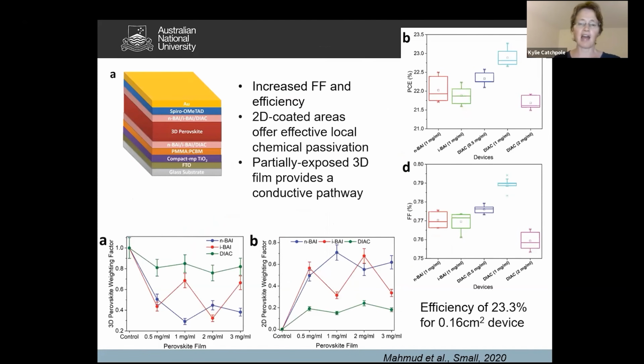Now, interestingly, there are other ways to achieve that. So what we're doing here is a quite different approach, but the net effect is actually very similar. So here we've got a perovskite layer that's passivated with a mixture of N-butyl ammonium iodide and isobutyl ammonium iodide. So that's what the DIAC means. That means the mixture. So we compared the cases where you're passivating with N-butyl ammonium iodide, where you're passivating with isobutyl ammonium iodide, and where you're passivating with that mixture.